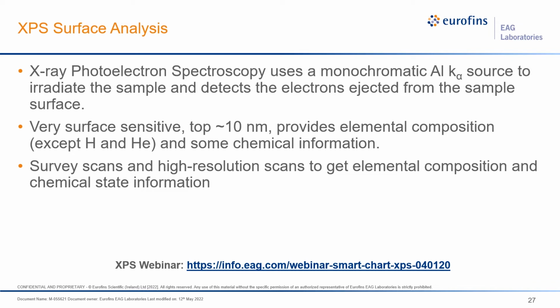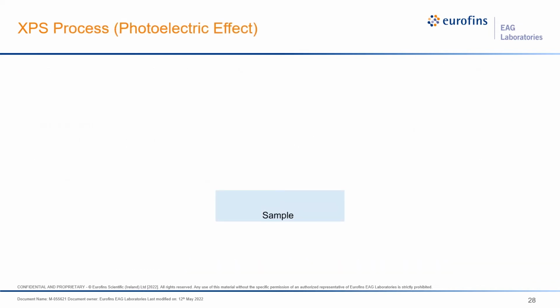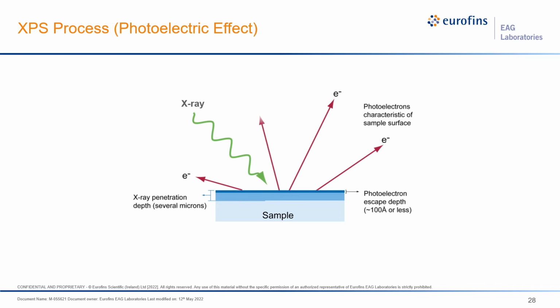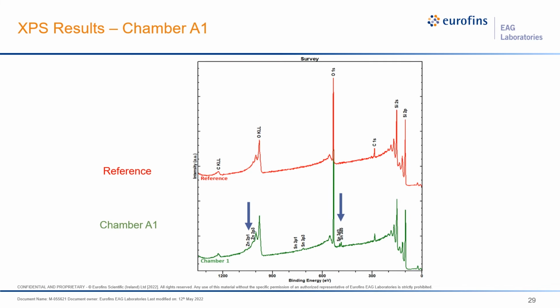All right, so the process is we put a sample into our vacuum chamber and we irradiate with an X-ray. And then the photoelectrons come out. And the reason that we have such surface sensitivity is we only are interested in the electrons that escape without having an energy-losing collision. So that limits it to about maybe twice the mean free path of the electron, which is why we get this surface sensitivity.